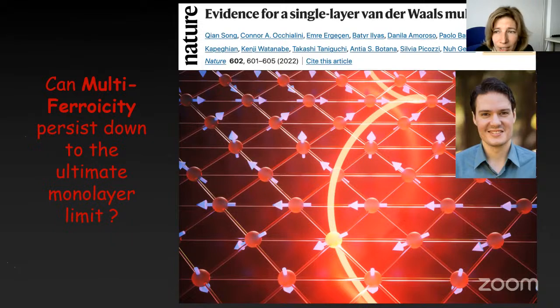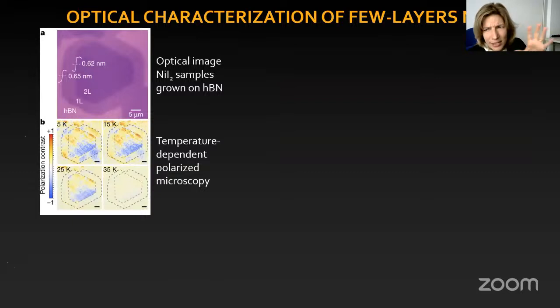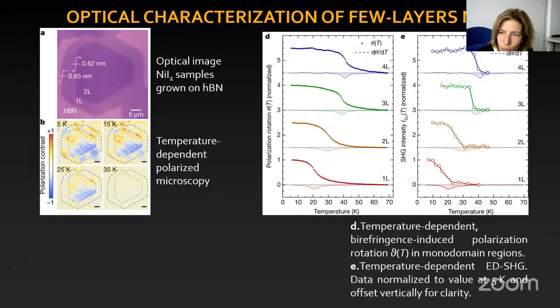In his group, they exfoliated NiI2, and then they characterized it via optical means and also by nonlinear optical effects, like second harmonic generation and optical birefringence.